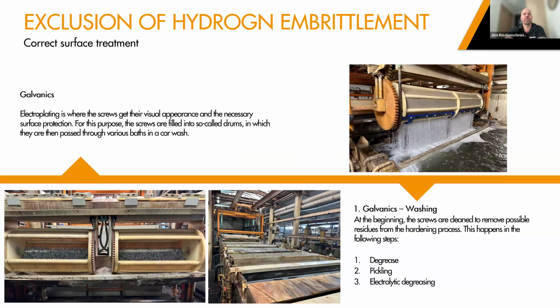In this case, we do galvanics. First of all, the hardened screw gets degreased, pickled, and degreased once more to be clean, so that you really can put the surface treatment onto the surface. They are put into so-called drums with satellites that prevent the screws from tangling up, because screws can really tangle up. We call it a hedgehog because they look like this. By this, we make sure the screws get an even treatment and don't become a big lump of screws.